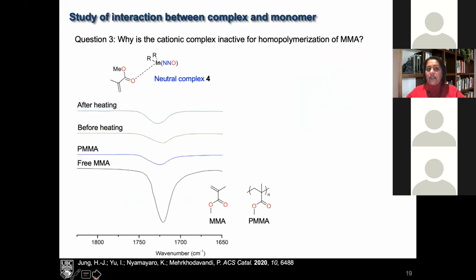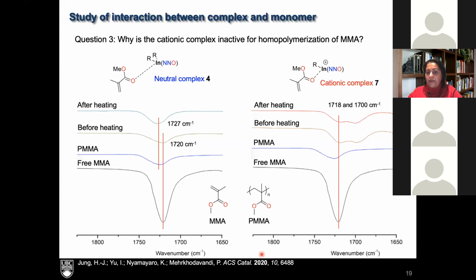Why do the neutral systems work and the cationic systems do not? You can see this using IR spectroscopy. The neutral systems are able to, if you see free methyl methacrylate, polymethyl methacrylate, you can see that the free methyl methacrylate is slowly converting to polymethyl methacrylate after heating. So this goes from here to here. However, when we look at the cationic systems, this doesn't actually happen. So when you go from free methyl methacrylate, instead of going to polymethyl methacrylate, they actually form a new band here. And this is, we believe, due to this cation acrylate interaction, which is basically shutting down the catalyst, which is why the cations don't work.